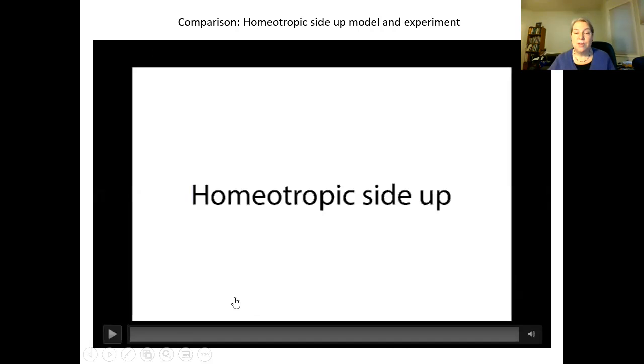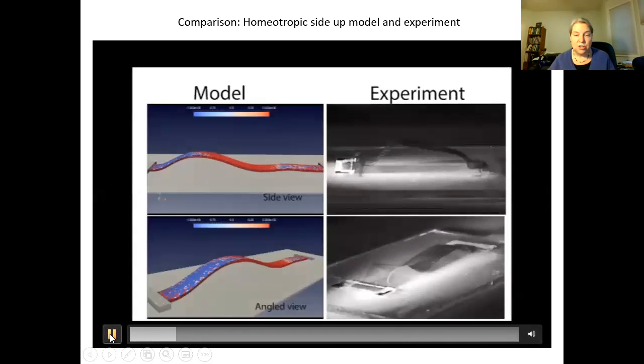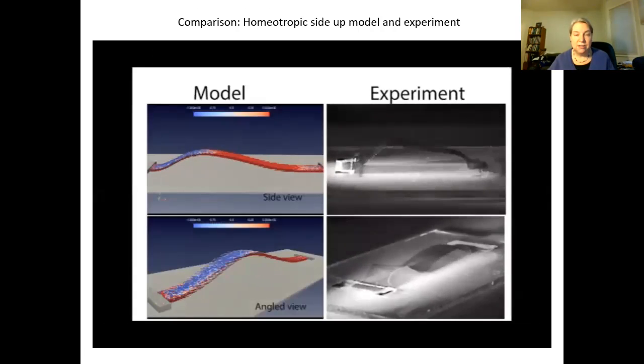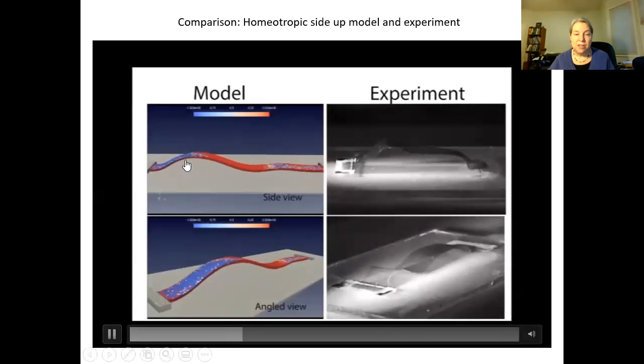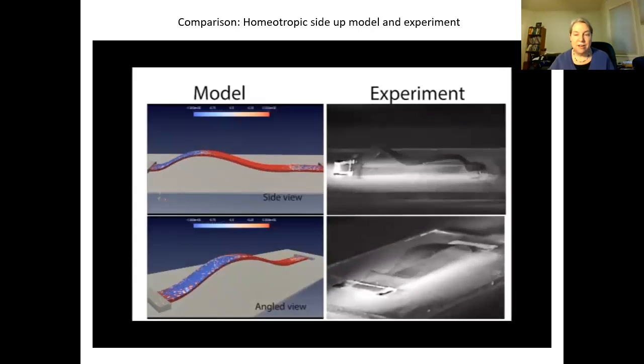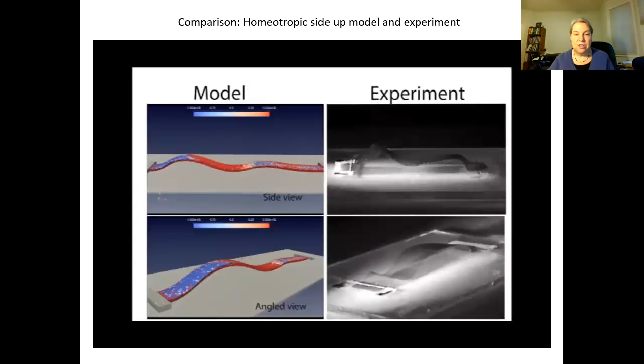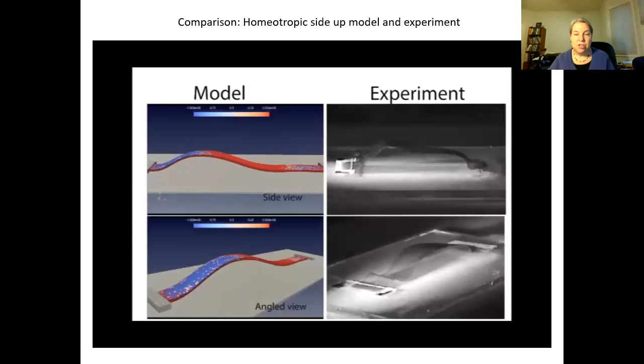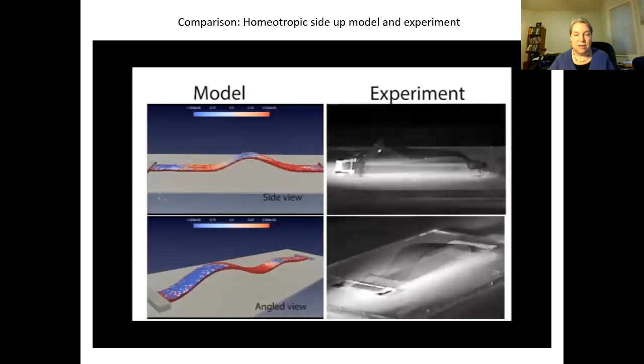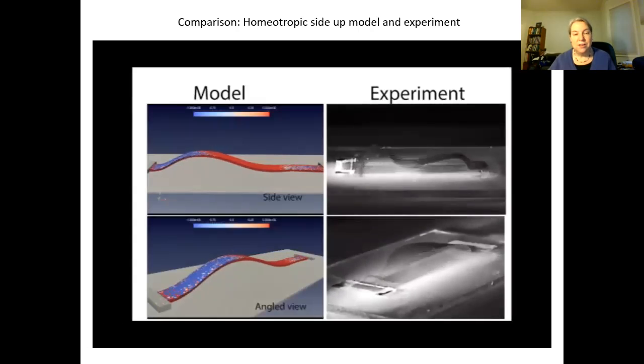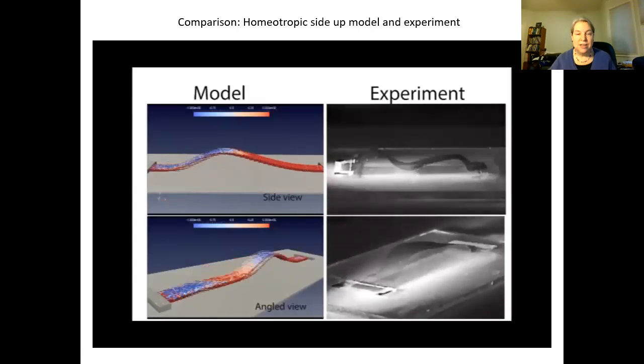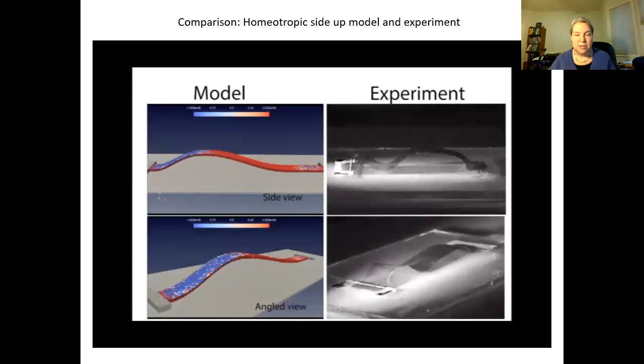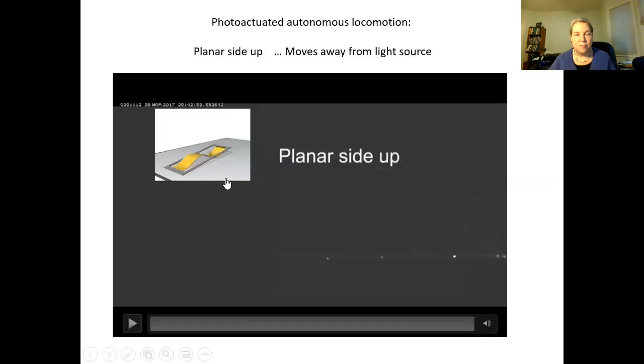If we do the same thing with the homeotropic side up, the waves move the other direction, which is to say toward the light, and much more slowly. Now the light is coming from the left side, and you can see that there's definitely a pop-through behavior, which is driving the wave motion. So slower and in the opposite direction. We had very simple assumptions in this model. It more or less reproduces the behavior in the experiment, not exactly, but pretty close.